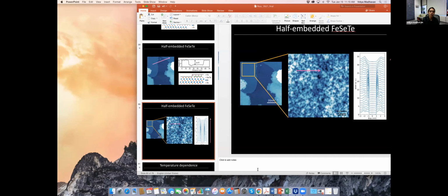So we're not growing it by evaporating Fe, Se, and Te. Instead, we're depositing only iron on top of bismuth telluride, and then annealing in a selenium-rich atmosphere, and that's it. And that's what gives you this. So the proof of the pudding is that you do that, and this is what you end up with. You don't end up with any excess iron. It's really nice. Okay, thank you very much.